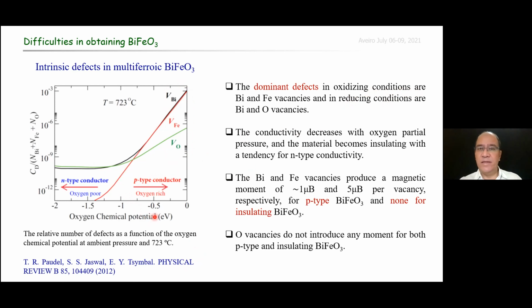On the other hand, in reducing conditions, the oxygen and bismuth vacancies dominate. It is interesting to note that the bismuth and iron vacancies produce a magnetic moment for p-type BFO and none for insulating BFO. In contrast, oxygen vacancies do not introduce any moment for either p-type or insulating BFO.